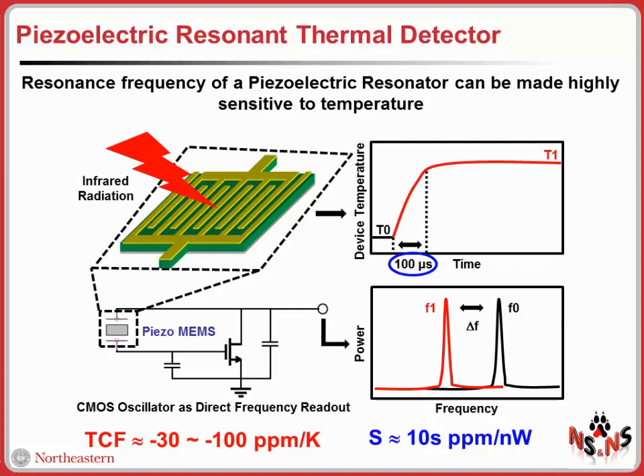So even if a small amount of infrared power is absorbed in the resonant body of the device, this infrared power will generate a temperature change that is quite large, given the fact that this plate is released from the silicon substrate, it's suspended, it's free to move, and therefore is very well isolated from the heat sink. But also this temperature variation has a relatively short time constant, due to the fact that the thermal mass of this nanomechanical structure is quite small.